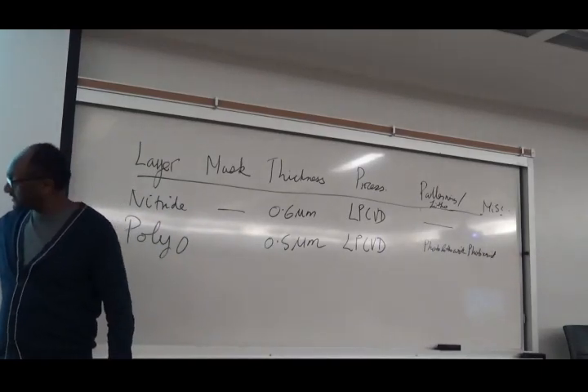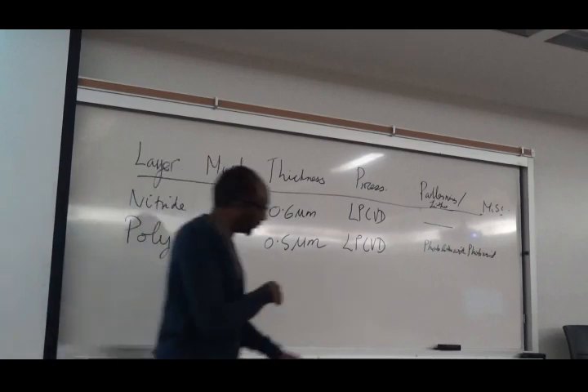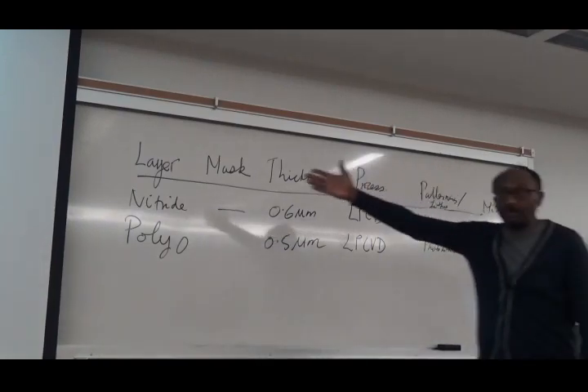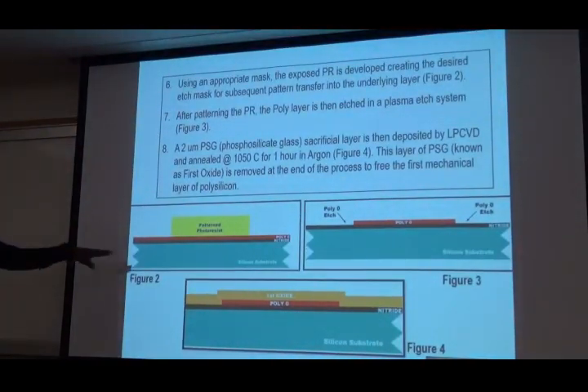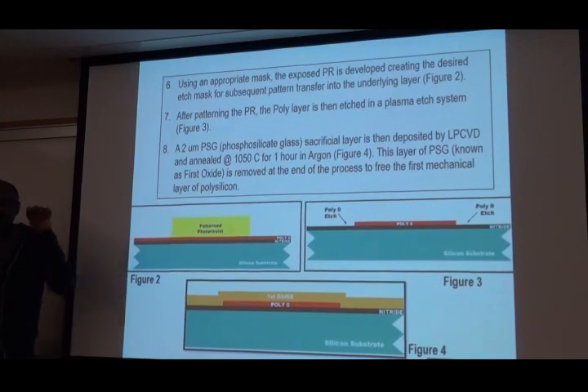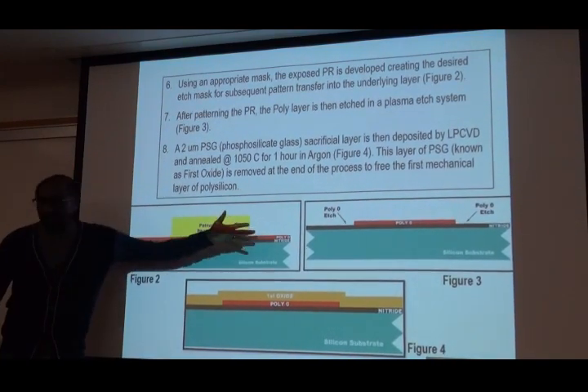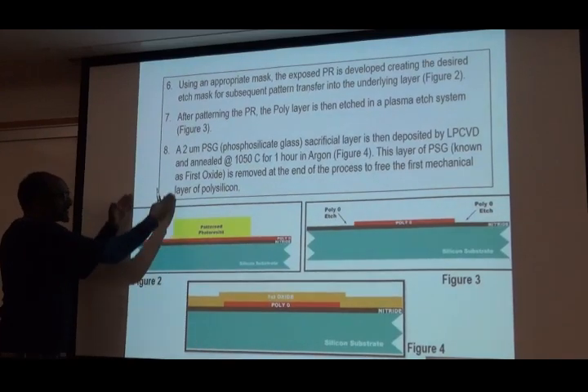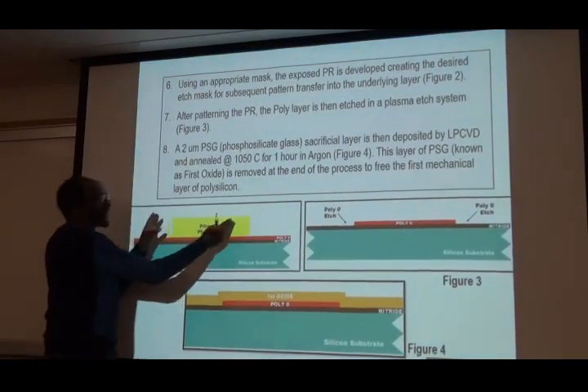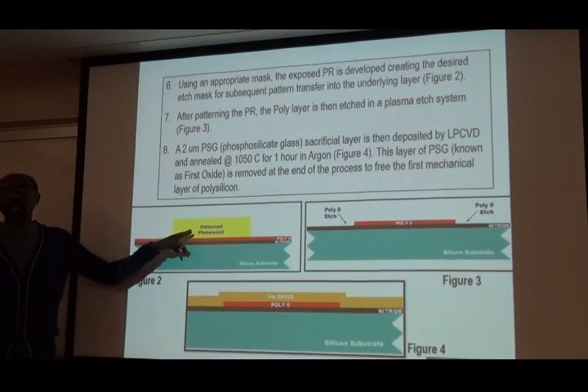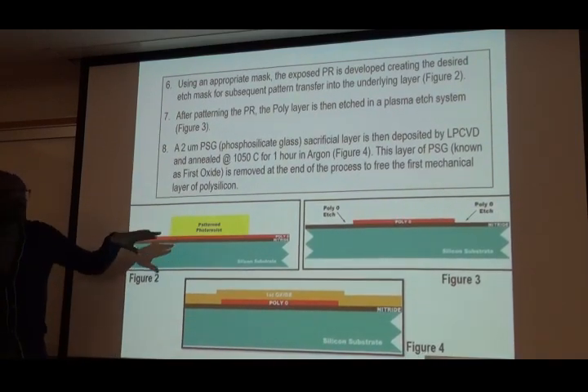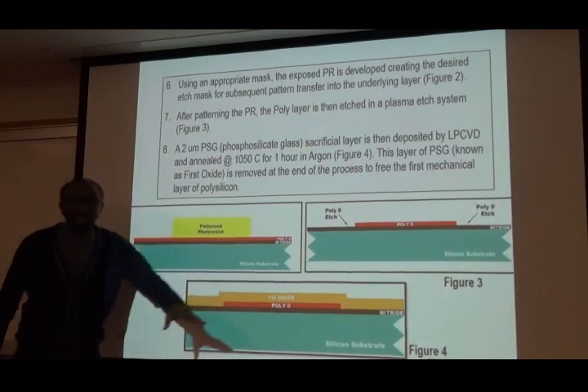So, then I put the photoresist because I want to pattern my wires. That's a photolitho that's captured in the table. So essentially that's what it says. Using an appropriate mask, they expose, develop, coating, all that kind of stuff. Then you get figure 2. Remember, when you do a litho, you put the photoresist, you put your mask, so apparently there was a dark one over here, transparent, no. So for this guy to remain, it has to be dark. Positive litho, remember. So positive litho, so this guy remains, the other guy is taken.